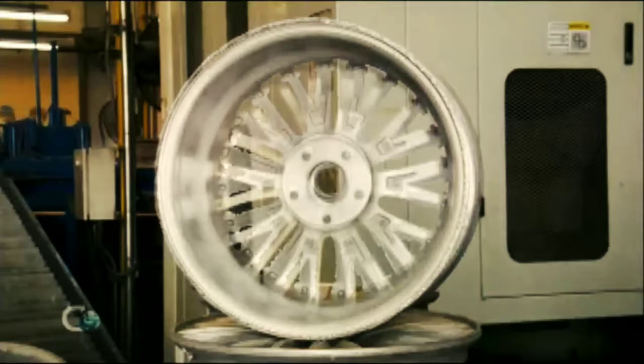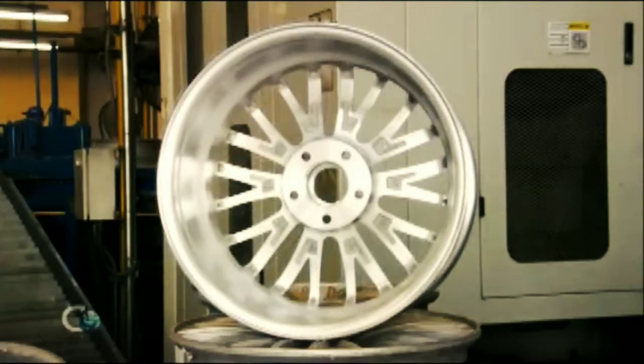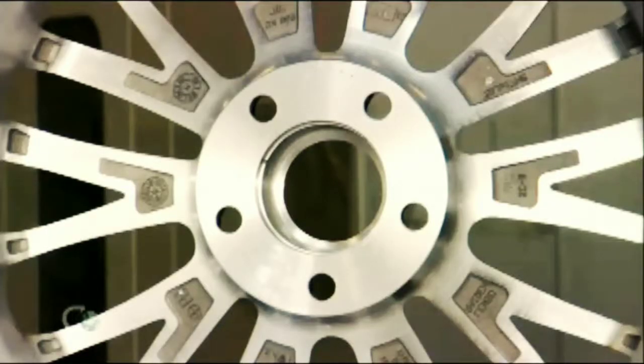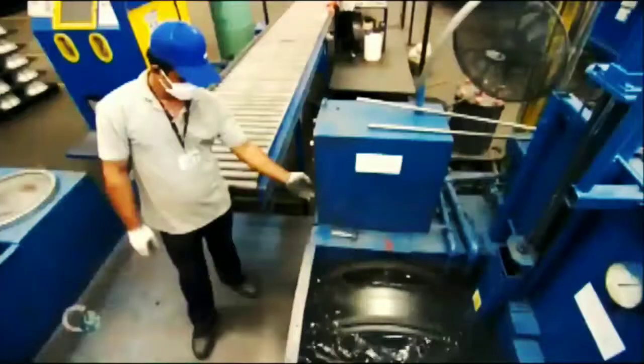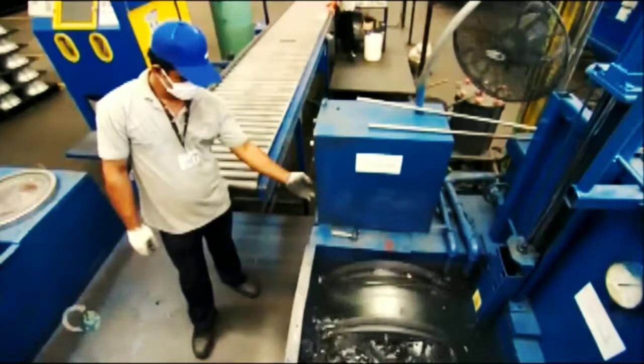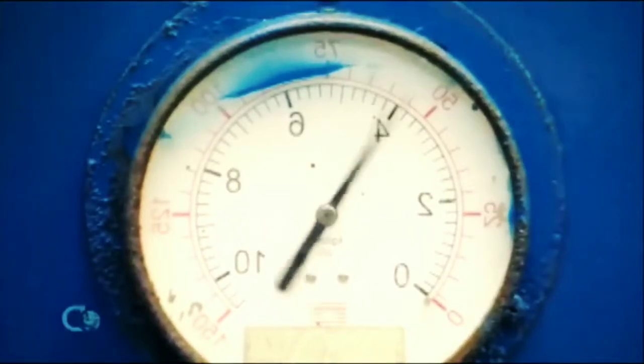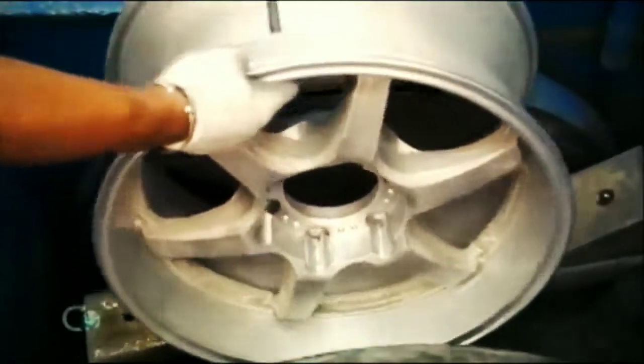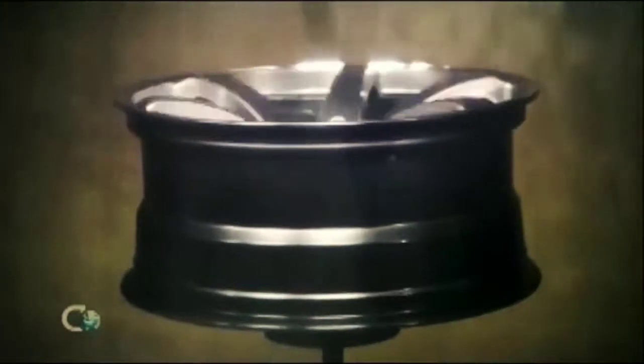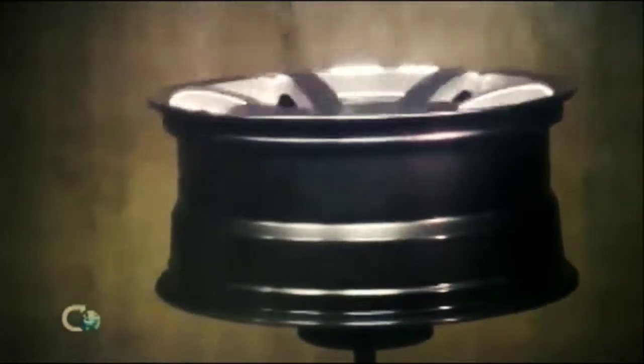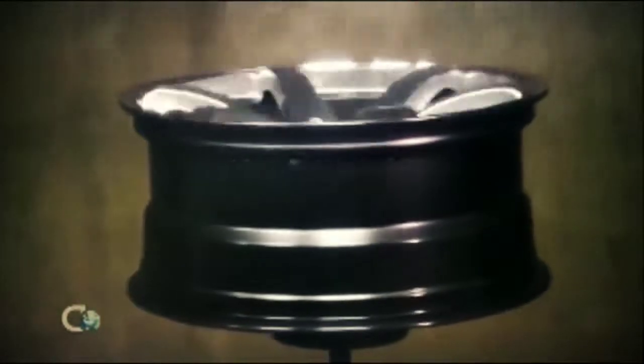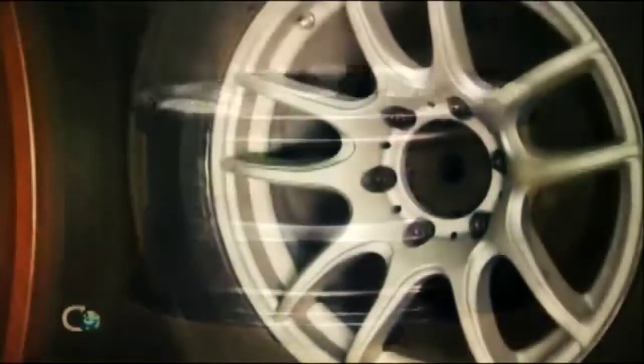The shape now finalized, it's time to test the wheel to make sure it's airtight. While pumping air into the wheel, they submerge it in water. Should any air bubbles appear, it would mean there's a pinhole in the metal or some shrinkage, in which case the wheel would fail inspection. No air bubbles, the wheel proceeds to the automated painting line. First, a base coat, then a coat of color, which can be anything from classic silver or black to a flashier shade. Then a clear coat, to protect the paint and prevent corrosion.